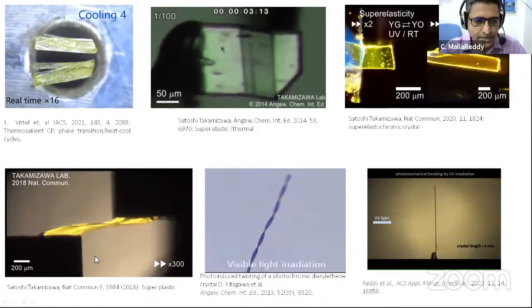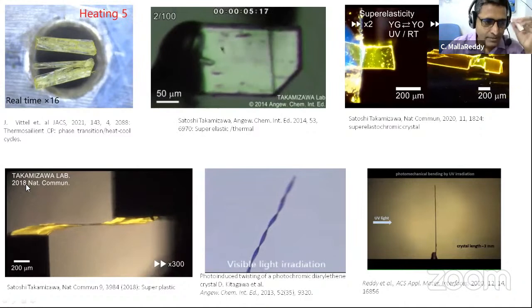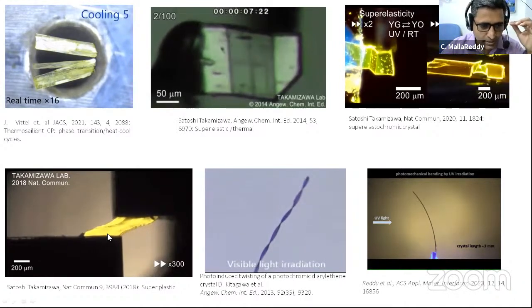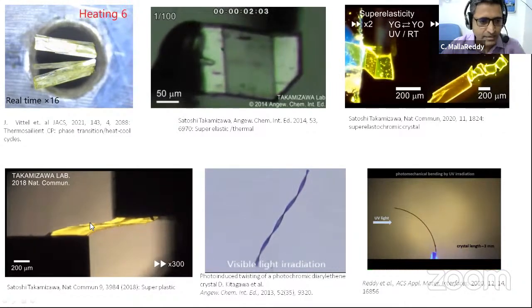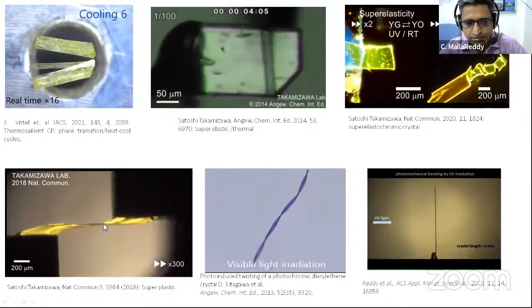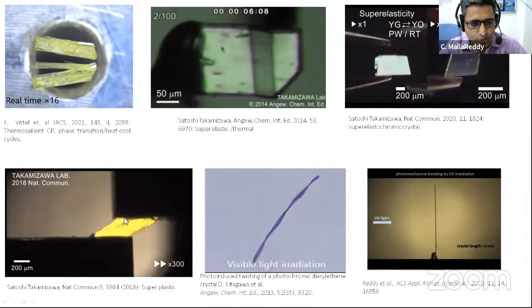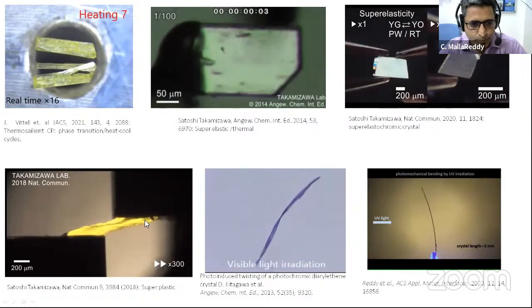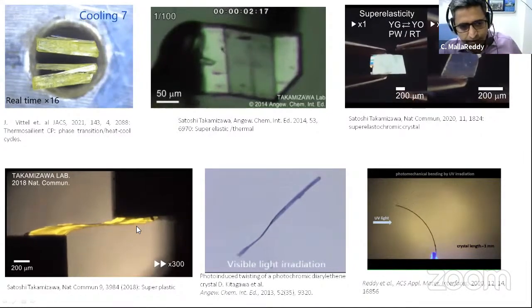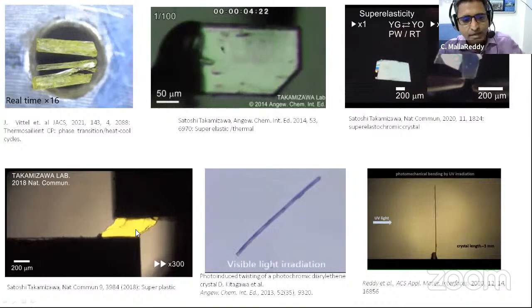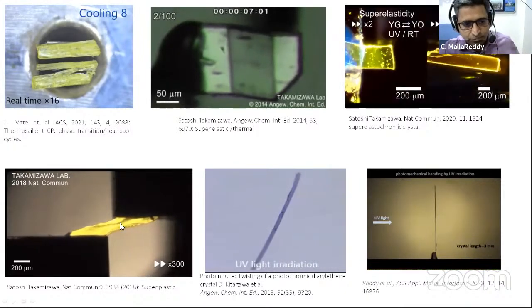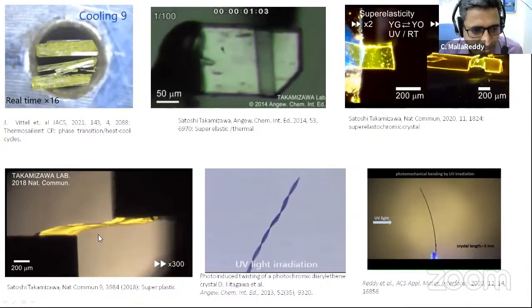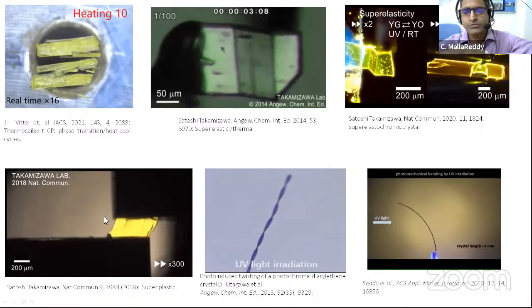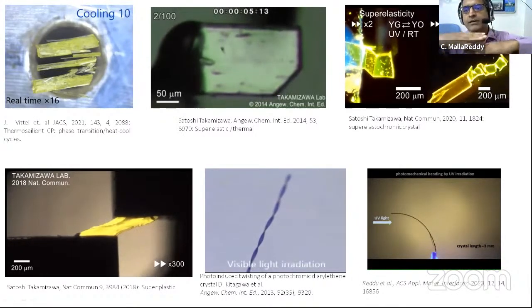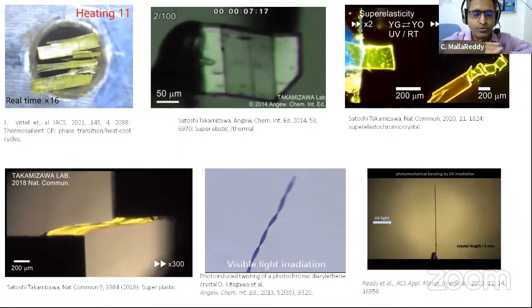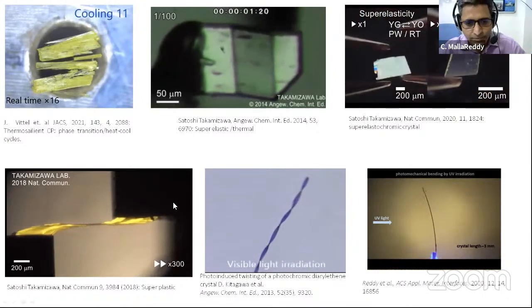So that's the challenge. So here again, the same Japanese group have shown that a crystal can actually be deformed to a large extent, as you can see here. So you put a crystal in between these two plates, and then you slide one, and the crystal behaves almost like wax. But they could even get the crystal structure at an intermediate stage. So they see that it has a layered structure, and the interactions between the layers are very weak, so you can basically slide them. So that's what they have shown.